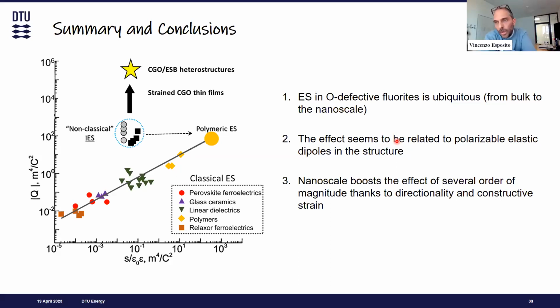Yes, I can say something in general about that. The materials we are analyzing are usually pure ionic conductors, especially in high oxygen content. Electronic conductivity in these materials is a possibility. It can arise in reducing conditions at high temperatures. So while in the presence of oxygen at high temperature, they are pure ionic conductors. In reducing conditions, they can become mixed ionic and electronic conductors. But this is again for high temperature applications, where the thermodynamics are completely different, and there is a pretty dynamic exchange of oxygen gas with the ceramic itself.